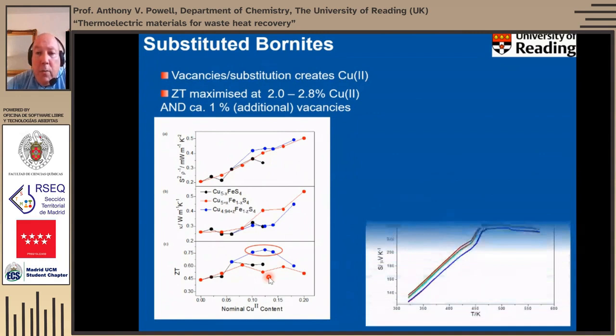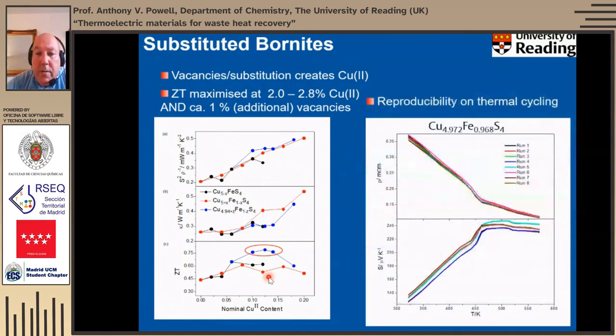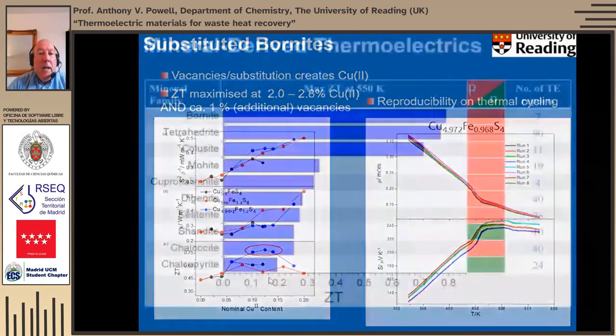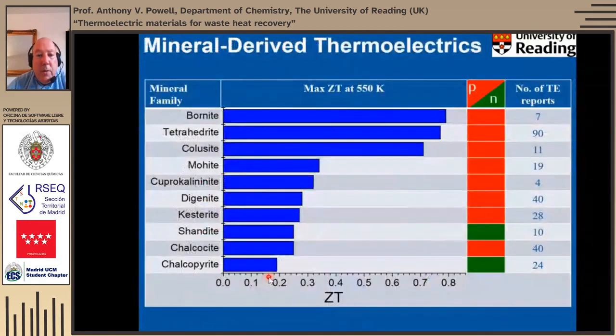And then finally, that reproducibility issue, we seem to have cured that as well, because if we do 8 runs here, we find that there's virtually no change from one run to the next. So it appears that the strategy of introducing some iron into the anti-fluorite structure has actually succeeded in terms of avoiding some of that degradation. So this just shows where some of those materials sit. I'm not going to spend a lot of time on this. I'd like to get to the summary slide in a moment.